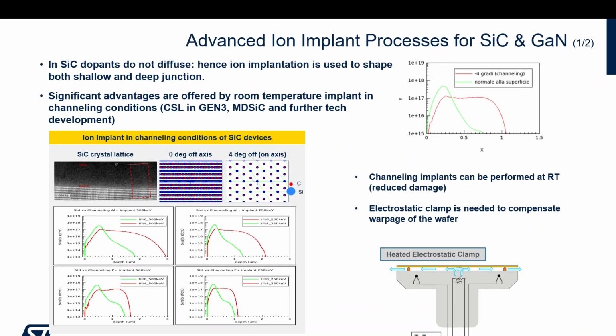In silicon carbide, one of the issues of ion implantation is linked to the fact that the dopant does not diffuse. So you can do a thermal process, but there is no diffusion, while in silicon, the shape of your junction is determined not only by the implant, but also by the diffusion.